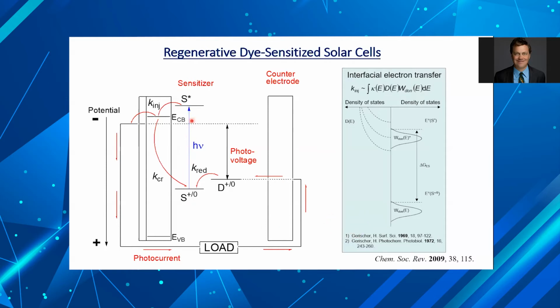But very simply here, starting on the left-hand side, the band gap of anatase TiO2 is about 3.2 electron volts, and that corresponds to photon energies in the ultraviolet region. About 2% of sunlight is absorbed by anatase TiO2, so it's a very small fraction, and it's not a useful material for solar harvesting. But if you attach a dye molecule to the surface, you can excite that dye with visible light. And if it's a strong enough photoreductant in its excited state, it can inject an electron into the conduction band, and that can give rise to a photocurrent and power generation.